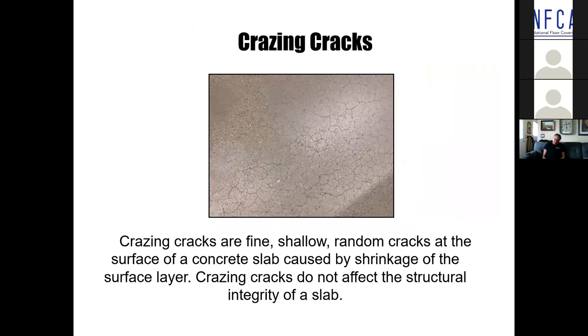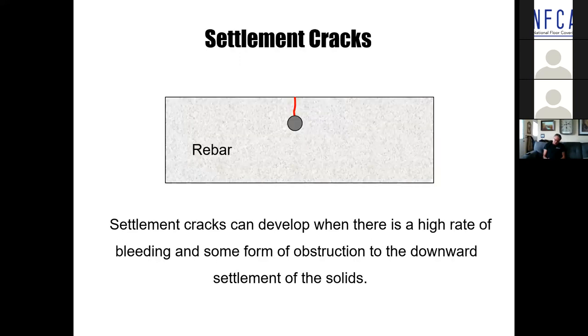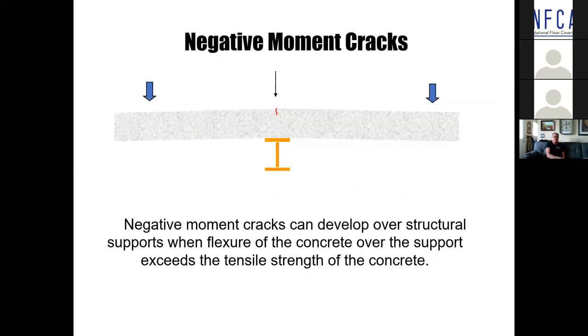Crazing cracks, not necessarily a defect. Very unsightly. A lot of owners panic when they see a crazed surface, but some of the best slabs that I've ever seen in my life, they've been in place for 50 years, have that type of pattern. Settlement cracks occur when the rebar is not properly positioned. Guys are walking on it, the concrete's beginning to set, they're walking on the rebar mat. You can get a crack over the rebar.